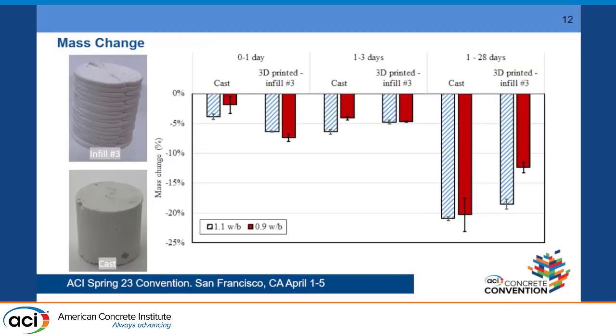It was a bit of a head scratcher to understand why this was happening until we finally decided to look at the mass changes of these specimens, not only when they are carbonated, but even before that. So between 0 and 1 days, because my samples are not hardened, I did not move them, I waited for hardening. Within that first day, my cast specimens are sitting inside their protective molds, so they're only exposed from the top for evaporation, whereas my 3D printed specimens have a much higher water evaporation.